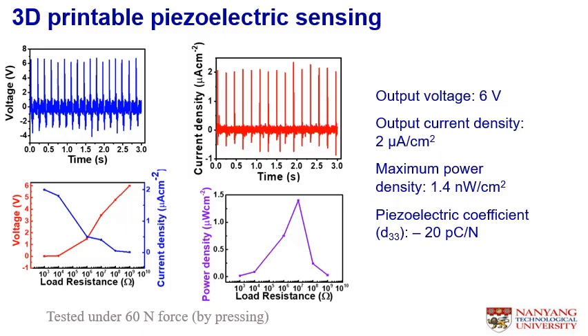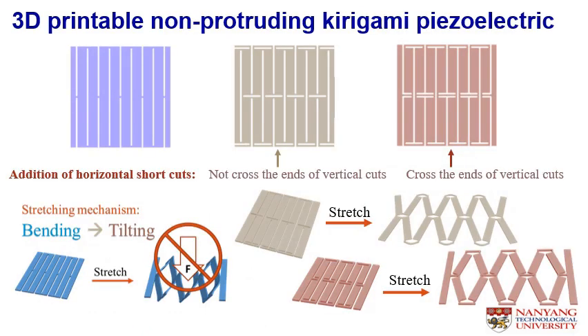It also shows a current density of 2 microampere per centimeter square, thereby giving a maximum power density of 1.4 nanowatt per square centimeter at the optimum load resistance. The material shows a piezoelectric coefficient of 20 picocoulomb per Newton. Utilizing the 3D printable formulated ink, we would like to realize a kirigami-based piezoelectric tactile sensing in a non-protrusion manner.